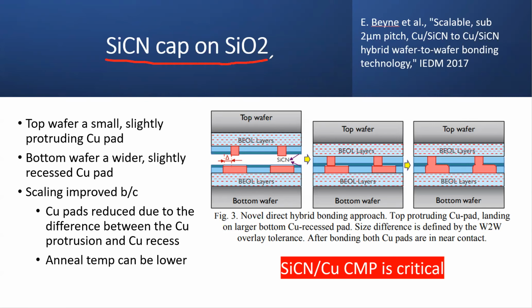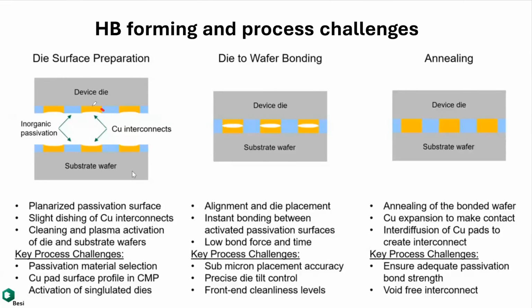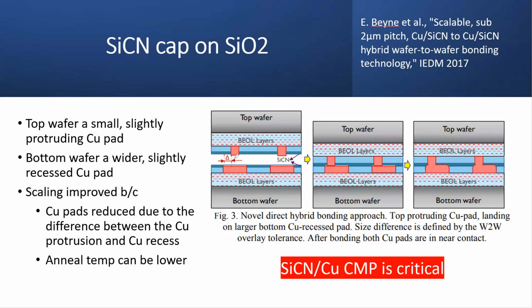And here is SiCN cap on SiO2. This is what I proposed. What I have in mind is that the top wafer is made slightly protruding out, and the bottom wafer is wider and slightly recessed. Here is recessed, here is sticking out. This is different from what we said here, where we want both recessed, a little bit lower than the outside. But I may say, no, that's not good enough. This is what I want: top a little bit sticking out and bottom a little bit recessed down, with the caveat that the top is smaller than the bottom. So when I land, I can always have a good landing, right?